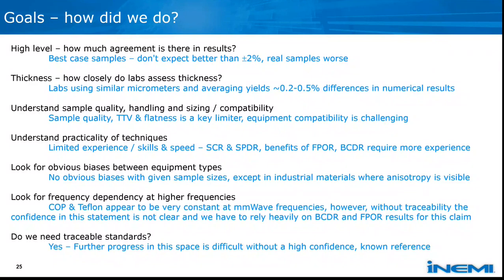I said for these best case samples, you really shouldn't expect better than plus or minus 2%, and realistically it's probably worse than that for realistic samples. So if you send your material samples off to a service lab to have them characterized, and the lab returns a statement that their results are more accurate than, say, plus or minus 2%, you need to understand that means their own lab can probably have reproducibility better than 2%. It has nothing to say about accuracy, or about the ability of another lab that also makes that claim to achieve the same result. So realistically, you can't expect better than a couple of percent today.